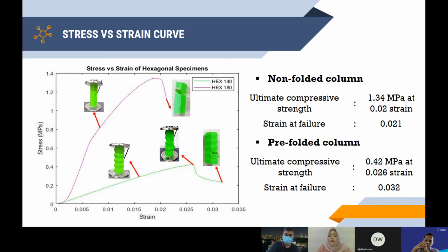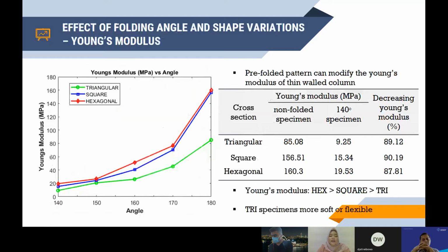However, the first peak, or ultimate compressive strength, is also decreasing from 1.34 MPa to 0.42 MPa. And the angle of 180 is the non-folded pattern. As the pre-folded pattern is introduced, we can see that the Young's modulus of a structure can be modified into a lower value. The table shows that introducing the pre-folded pattern decreases the value of Young's modulus.